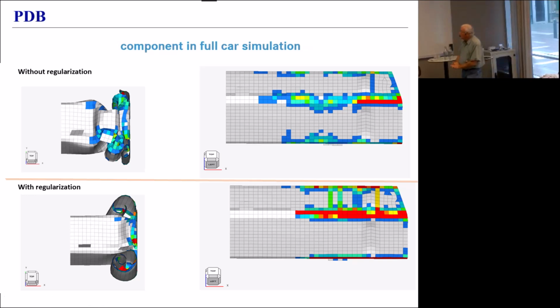You see a part here of a component in a full car simulation, and on the top you see a deformed shape, and the red dots that you see in the middle and in the right-hand side plot are eroded elements. So you see a buckling mode of that extrusion profile, and you see a moderate amount of failure. In that simulation, we had no regularization, and it behaved perfectly. With regularization, you get the nonsense that you see on the lower row. Massive amounts of erosion, way too much failure, and basically a shear off of the top plate from the rest of the profile. It opens like a can of sardines. That's not what happened. That's not what happened at all.